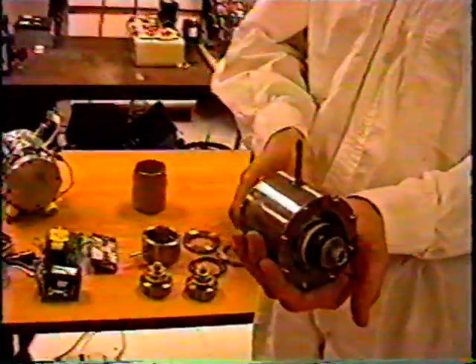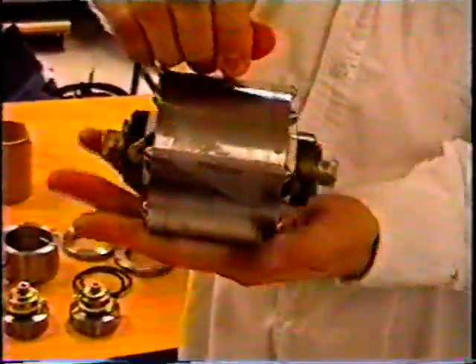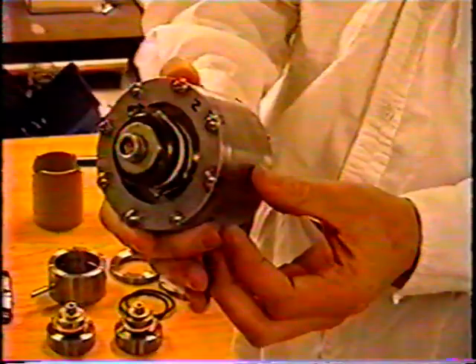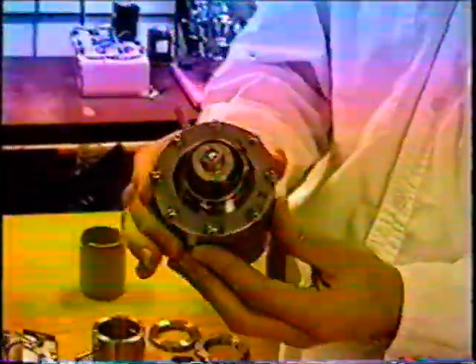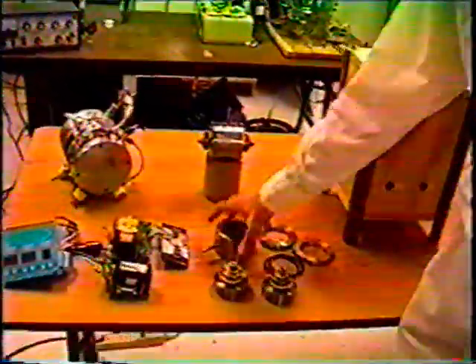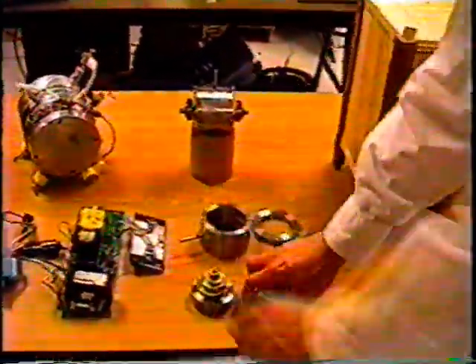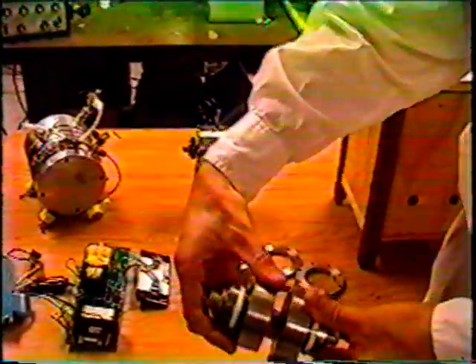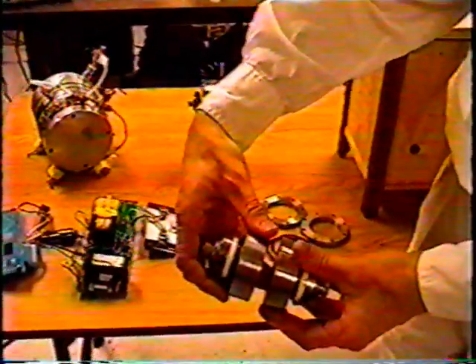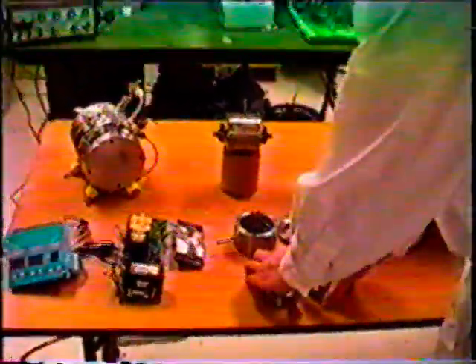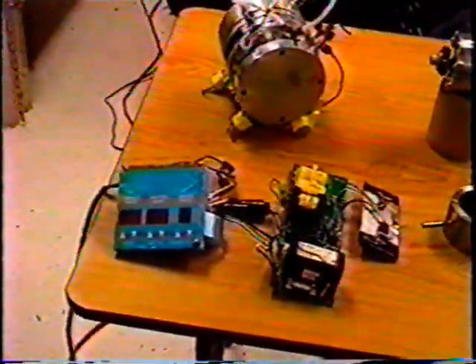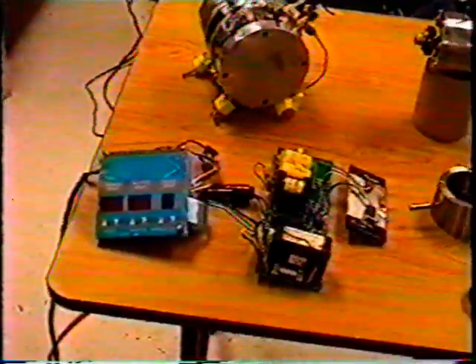So we came up with a smaller reactor right here, which you can easily see. Piezoelectric elements at both ends of the stack are mounted into a very compact stainless steel structure composed of these pieces here, as you see on the table, a hollow core, which then places these two piezoelectric stacks about 1/4 inch apart for a 2.5 inch cavity diameter. And both of these reactors are run with commercial ultrasonic electronics taken out of a jewelry cleaner.